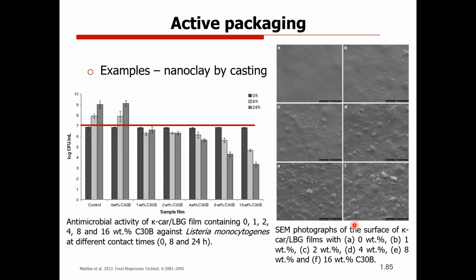If you remember, I showed you our tests adding some nanoclays by casting in polysaccharide-based films. Besides the water vapor permeability and carbon dioxide and oxygen that I showed to you, we also tested the antimicrobial activity against Listeria. To remember, we added only one nanoclay, Cloisite 30B, but at different concentrations: 1, 2, 4, 8, and 16% in the matrix, and we saw that we have a bacteriostatic effect for 1 and 2%, and only for 4, 8, and 16 you have this antimicrobial capacity and the reduction of this growth. And that happens more clearly at 24 hours. So you have 0, and then you have 8 hours and 24.